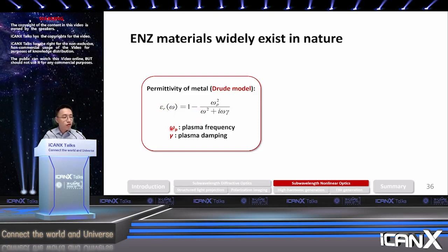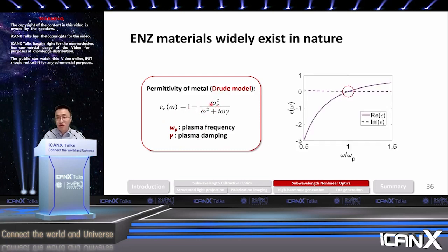So here there are 2 important parameters. One is the plasma frequency, omega p, of the material, and the gamma, I mean the plasma damping. Okay, if for now we ignore this plasma damping term here, you'll find that when the angular frequency of the light exactly equals the plasma frequency of the material, you'll find that 1 minus 1 equals 0, right? Then at the plasma frequency of the material, you'll see that the real part of the permittivity will cross 0. Of course, due to the finite plasma damping, we'll still have some finite imaginary permittivity in the material.